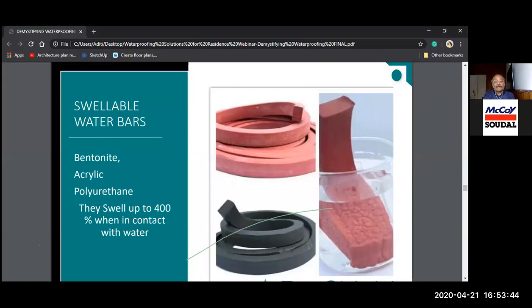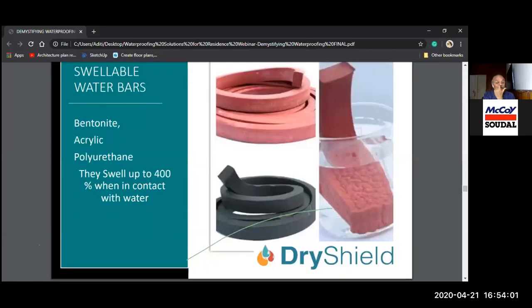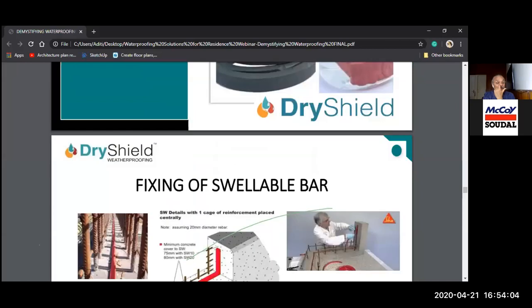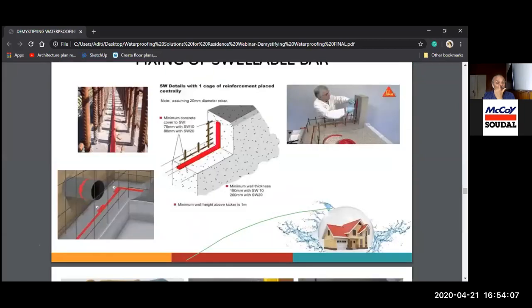They can be bentonite, acrylic, and they can swell up to 400% when in contact with water. So as soon as water touches it, it starts swelling. So this is how you fix it. If in a concrete cover of 75 mm, you can use a 10 mm or 20 mm wide bar. And you can see on the left hand side where the cage has already been made. In the center, you can fix this water bar. Again, depending on the width of your wall, it has to be selected.